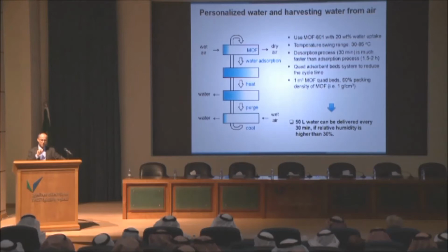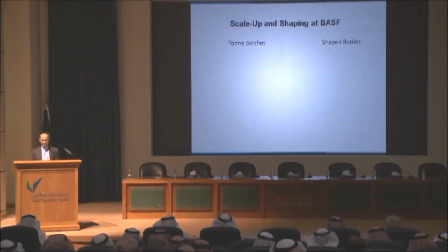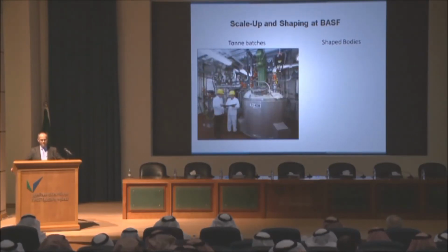So this is a huge application, and the key feature here is that the design of the material has to be in such a way that the material can operate at a very specific pressure and have a very sharp isotherm rather than a shallow isotherm. That allows you to take the water in and fill the pores very quickly and then release them. So that's something that we are working very hard on, and we are now trying to build a demonstration model, a small laboratory pilot, to demonstrate that this really works in real quantities.